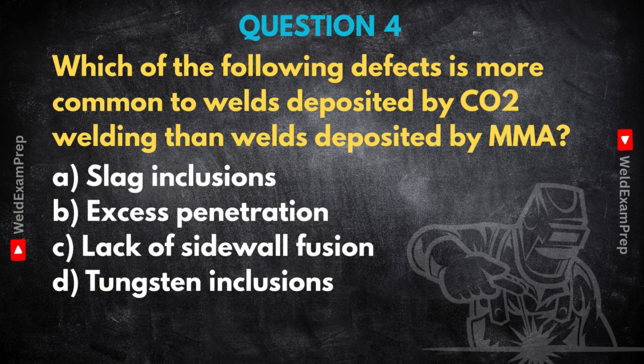Okay, think about CO2 welding, like the GMAW, versus MMA or stick welding. Which defect is more typical for the CO2 process? The answer we're looking for here is C, a lack of sidewall fusion. And this is a really serious one. It means the weld metal hasn't properly bonded, hasn't fused, with the side of the joint, the base metal.